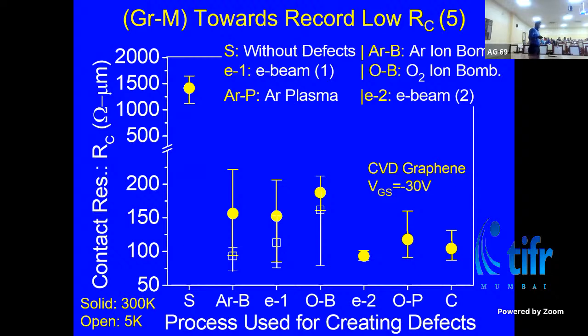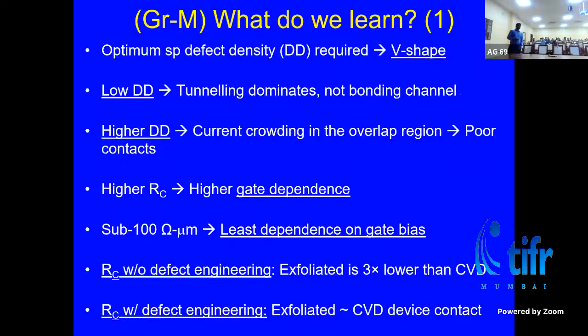Okay, so again, as a function of all the engineering methods that we experimented, we demonstrated significant reduction in the contact resistance, of the order of 100 ohm micrometer or less. Right. So if I summarize everything that we have seen so far, I have talked about the defect density. That's when you have an optimum required defect density, you see a V-shaped characteristic, and the V point is the optimum point. When you have low defect density, you have tunneling dominated contact.